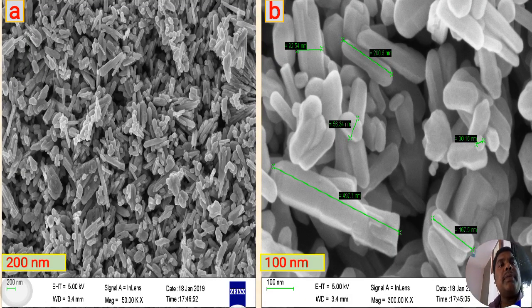Now see, that is the FESEM result at 200 nanometers and 100 nanometers, and here is a clear-cut indication at 100 nanometer. We see the formation of porous-like morphology as well as rod structure, with an average diameter of 50 nanometers and a nanorod length of approximately 350 nanometers. We see that there, and we confirm with XRD again.